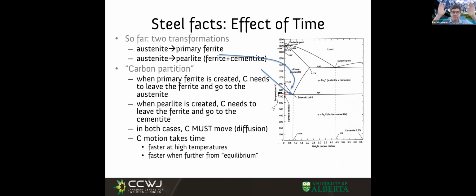If we're going from austenite, for example, at 0.2% carbon, it's a lot more than ferrite can take. So the austenite is happy. The austenite says, oh, I only have 0.2% carbon, I'm like 10 times less than what I can take, no problem. And then all of a sudden it gets into ferrite. And ferrite says 0.2% carbon, you're crazy? This is like 10 or 100 times more than I can take.